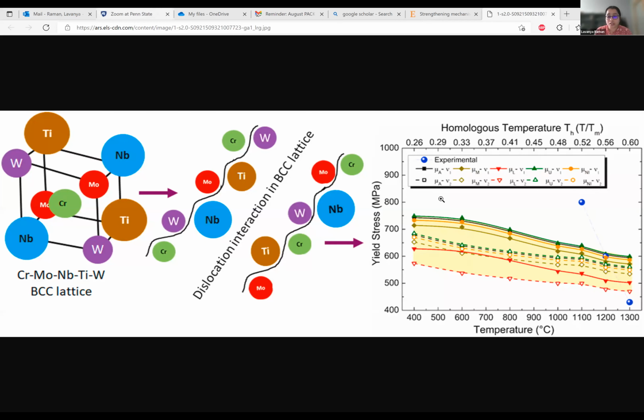As you can see in this figure, we tried to estimate, this is only for the solid solution, how the dislocation interacts with the BCC element. As you can see, there is a wide range, so we cannot really say how much comes from the solid solution exactly. From the equation, we can understand that more than 50% is the contribution from solid solutioning. But depending on your Poisson's ratio and shear modulus, it varies over a very wide range, because for these alloys it is very difficult to estimate the experimental Poisson's ratio and shear modulus.